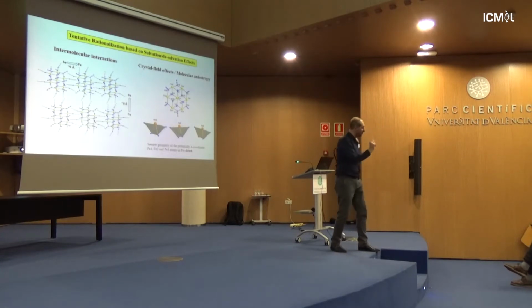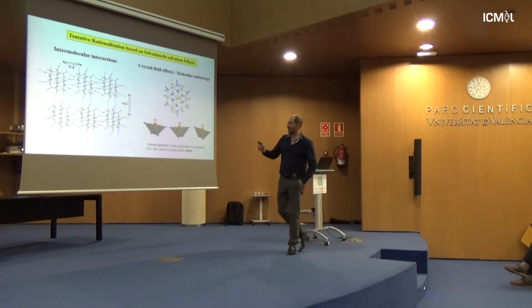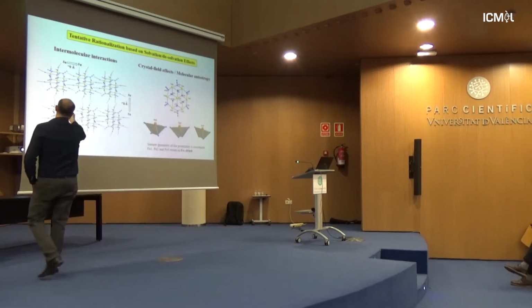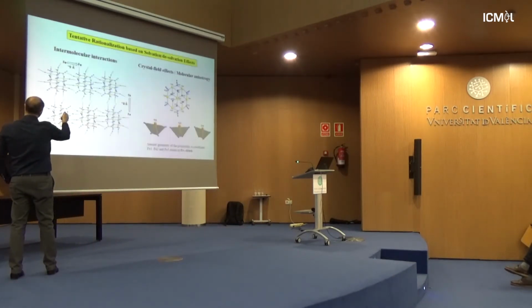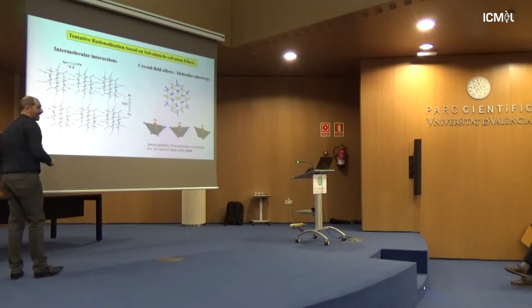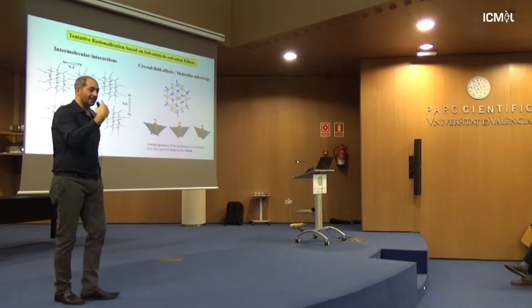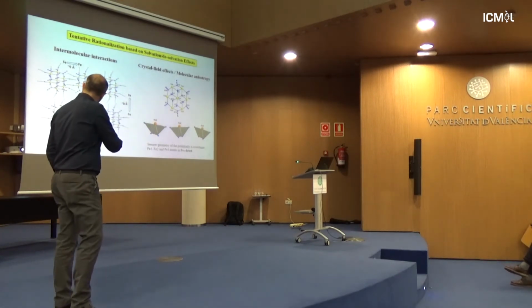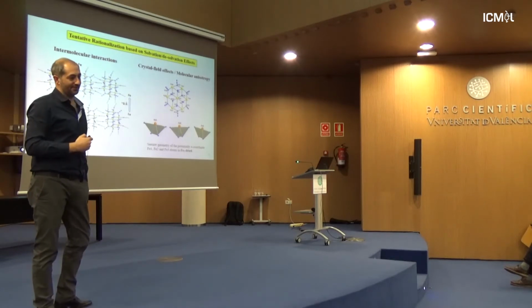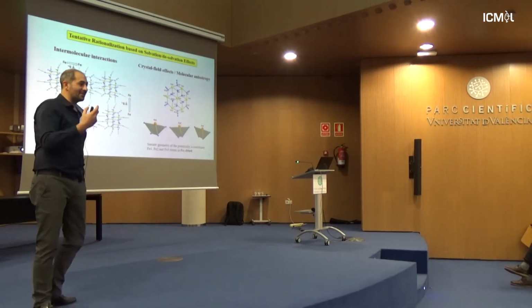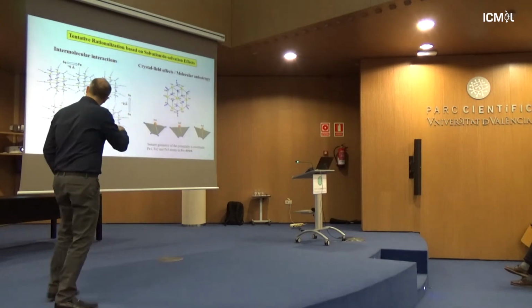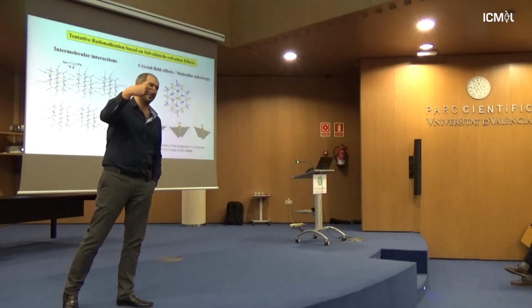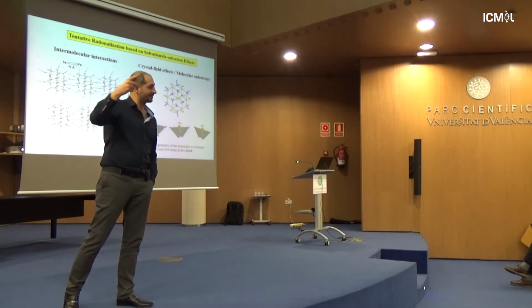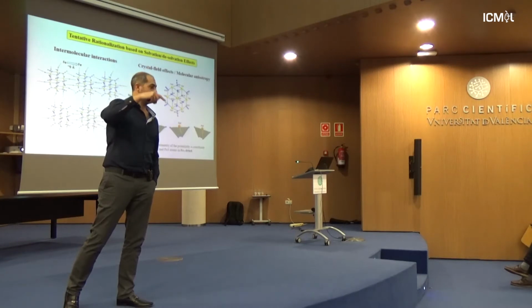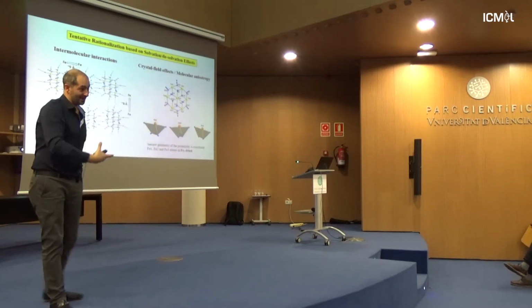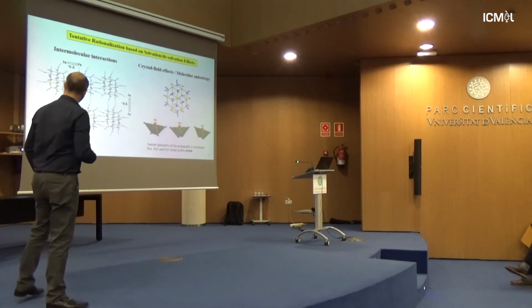Option number two, it's not impossible that upon drying and removal of those acetonitriles, some of these tails of azides become bridged with real bonds, and that bridge connects those clusters in the crystal. In this case, then you expect to have something like SMM from the cluster and single chain magnet between the clusters, which could explain the two different relaxation processes. Keep in mind, these are all scenarios. We don't have so much data at this point, but we would like to investigate those further.